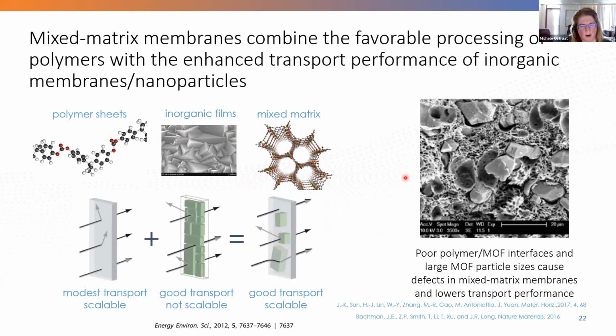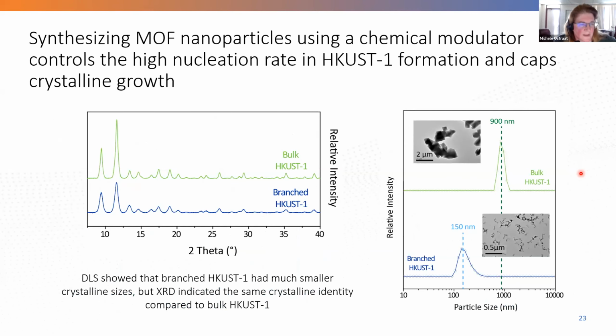Now, I think MOFs in membranes have gotten somewhat of a bad rap because it's very important to control the interface of the polymer and the MOF. If you don't do that, you basically get a lot of defects in these mixed matrix membranes that lower the transport performance. Additionally, you need to be very concerned about the size of these MOF particles to make sure they don't get too large in these systems as well. So when I was at Aramco, we developed a number of synthetic steps to modify and customize MOF nanoparticles using chemical modulators that were able to control the high nucleation rate of some of these MOFs, these HKUST-1 MOFs, and control their size and cap their crystalline growth.